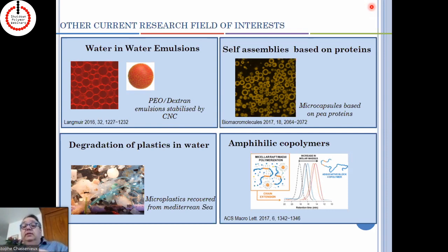electrostatic and steric repulsion. The thing that we have done a long time ago is that by playing with the dynamic, if you take a system which is completely frozen, and you take this as the emulsifier, you can control the number of latex particles that you are able to transform, because each frozen micelle will turn into a particle. Now, if you have a system which is dynamic, you no more have this control, and you have something that really behaves like an emulsion polymerization, which means that you need several micelles to obtain one latex particle.